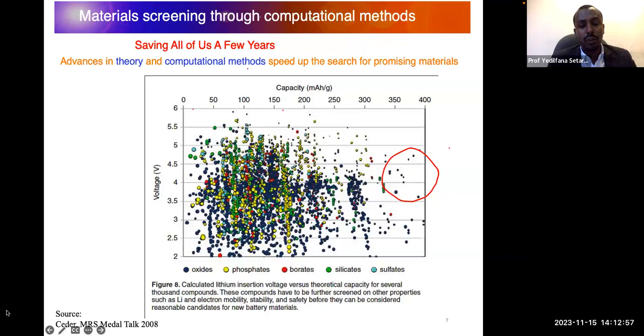For instance, this group has done a lot of computational work, using advanced computational tools on different compounds, oxide, phosphate, borate, silicate, and sulfate, to search for a good or promising cathode material for lithium-ion batteries. They calculate the lithium insertion voltage versus the theoretical capacity. As you can see inside the red circle, the materials are identified as promising for application as a cathode in lithium-ion batteries, with a voltage above 3.5 and a capacity above 350 milliamp hour per gram. These are really promising, and this is obtained through only computational methods.